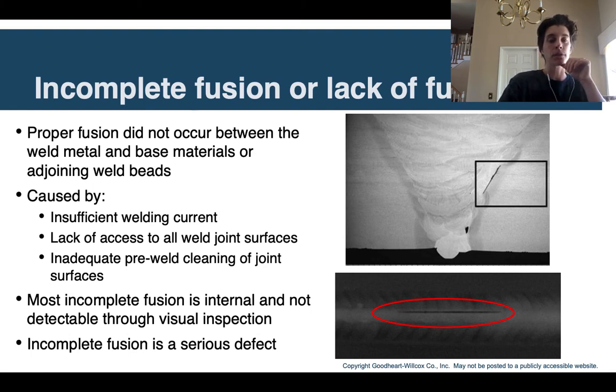A couple of different causes for this. Too low of a current, or amperage. Maybe a lack of access to all weld joint surfaces, or maybe you had a super tight groove, or a little bit too small of a V and you couldn't get your welder in there very well. Inadequate pre-weld cleaning of the joint surfaces can be a problem too. You had oil or paint or something like that getting in the way.